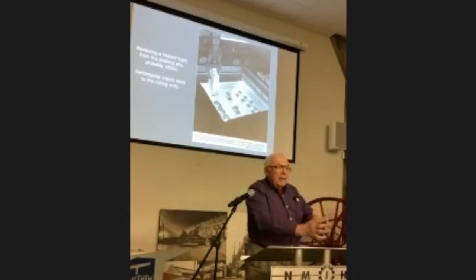As the product solidified, you had the iron-rich stuff solidify first on the outside, and as the solidification advanced inside, the crap and the gas was pushed to the inside, and that was in the center. So when you took this ingot, and with almost always sheet product that we use rim steel for, you rolled it, you got beautiful surface. But as soon as you had corrosion that went through to the middle, it went to hell in a handbasket.